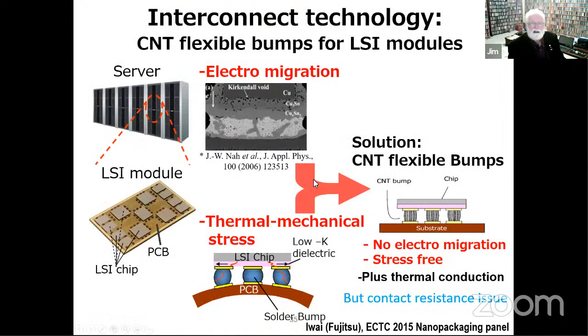So again, this is carbon nanotube bumps for interconnection for flip chip and so on. The carbon nanotube will resist electron migration and also can be regarded as essentially flexible, so there's a lot of fine lines here. So we can get effectively low electrical migration and stress-free, and also a high thermal conduction. But there is a contact resistance issue.